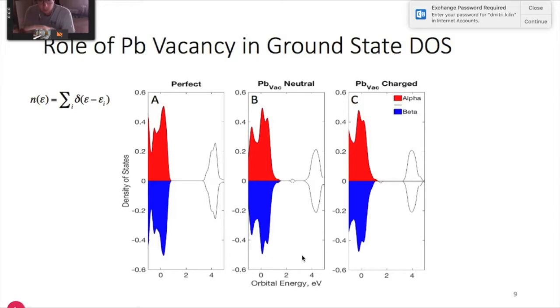Now, the other important thing about the system we were looking at here is that once we created this lead vacancy, we're adding an additional electron to the system, creating an open shell spin state. And so now we can see that the spin up and spin down components in the right density of states figure are no longer symmetrical. For the beta or spin down in blue, there's a small unoccupied state created just above the valence band for the system.